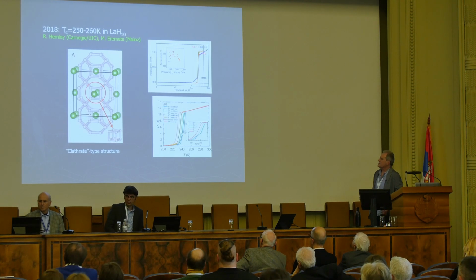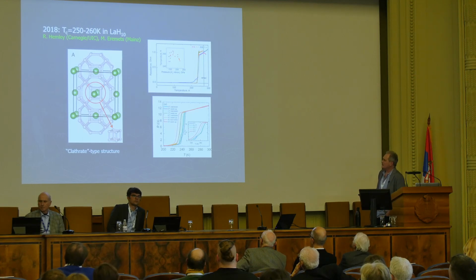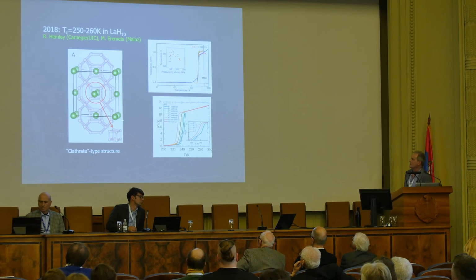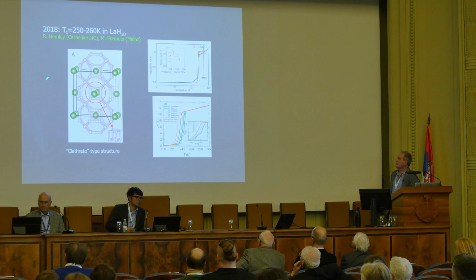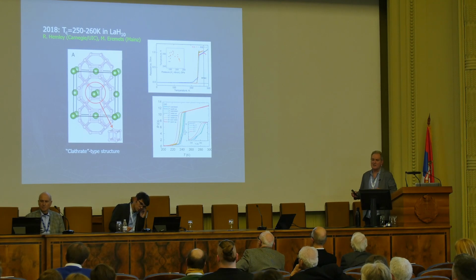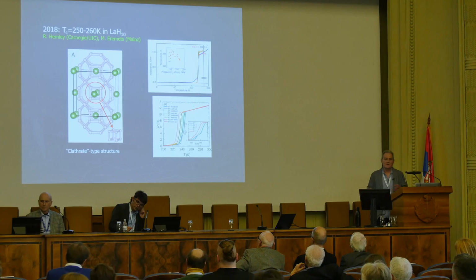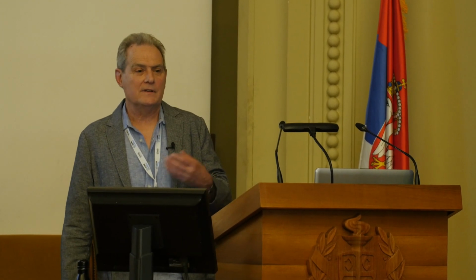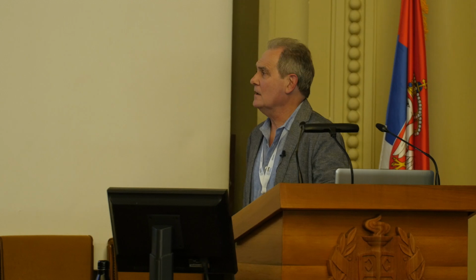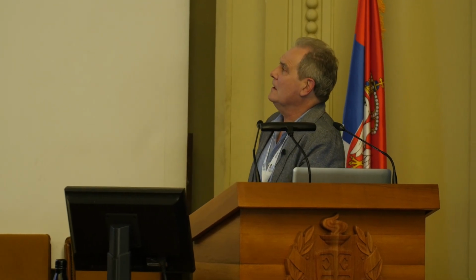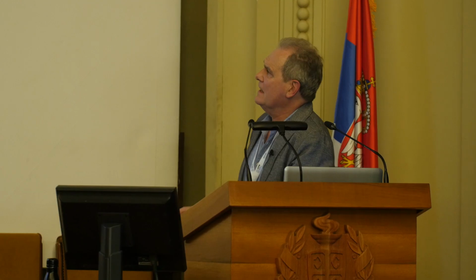So the discoveries in this field continued, not as rapidly as before because you need very high pressures to be able to do this. This is a material, lanthanum hydride, discovered by Russ Hemley and then confirmed by Eremets, where you have this cage structure. The idea is you have as much hydrogen as you can pack in. The hydrogen vibrations are very high frequencies, and that will give you a large omega log, or phonon energy scale on the average. And so that went up to 250, 260 Kelvin.